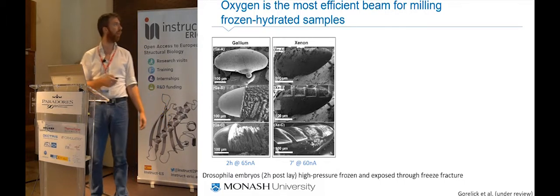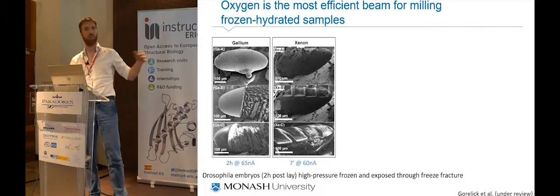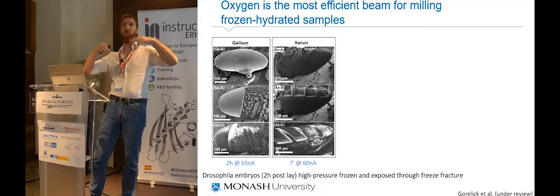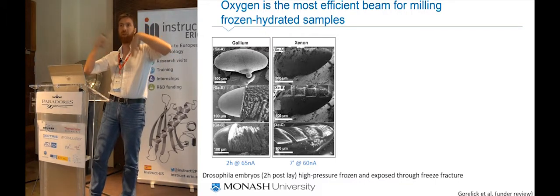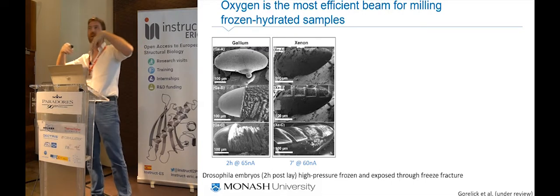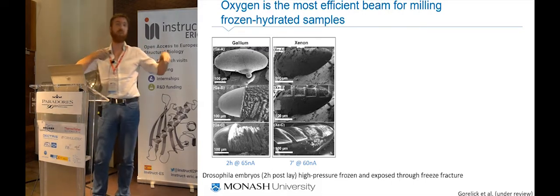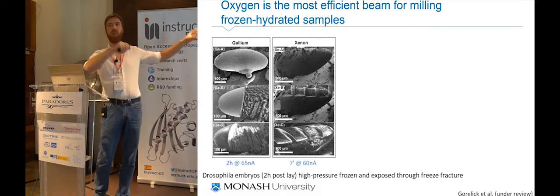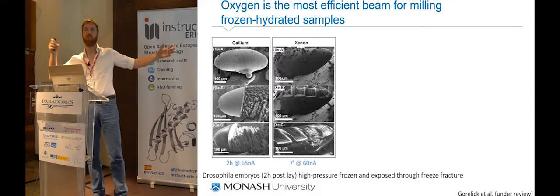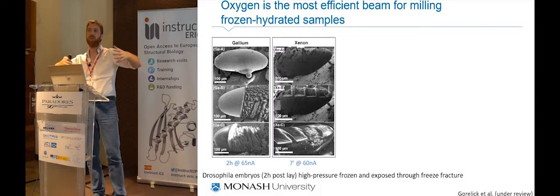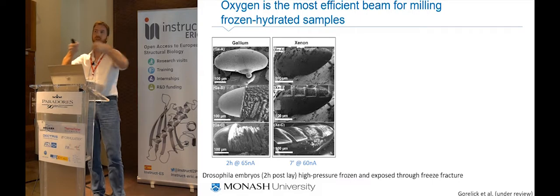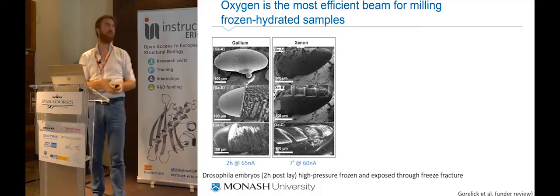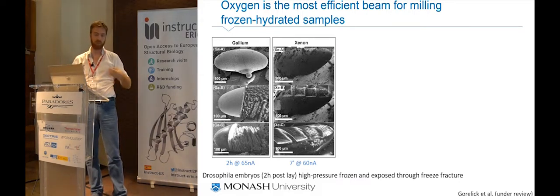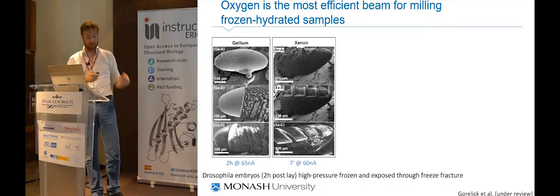It's not very usable. The reason is that there is a lot of redeposition, and we are curing the redeposited material, so it's getting harder and harder and harder. On top of that, it's charging. The whole thing here, which is not conductive, becomes positively charged, and I'm shooting a positive beam. Everybody knows that you can't quite reach very easily if you've got two positive charges. I mean, they won't collide.